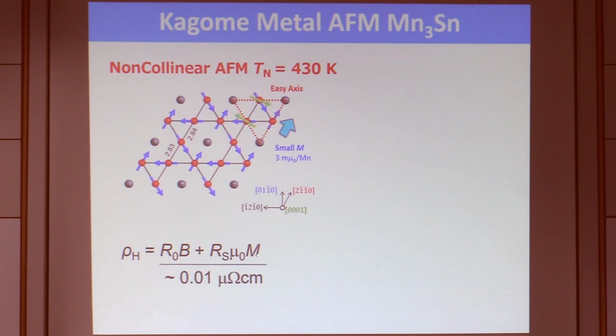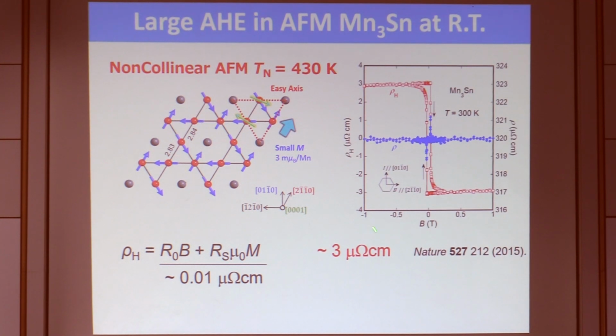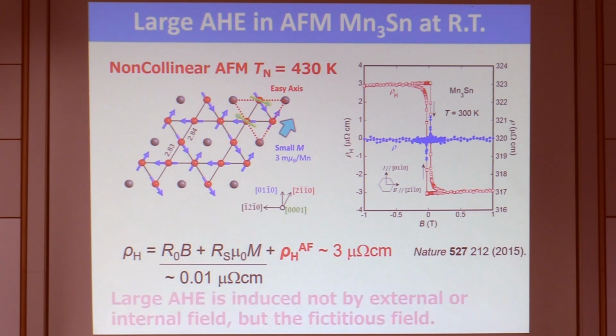According to this empirical rule, this would only introduce a 10 nano ohm centimeter. But in reality, we found that it is a few orders of magnitude larger than what you expect based on magnetization. So this tells us there has to be a new contribution to this Hall effect.